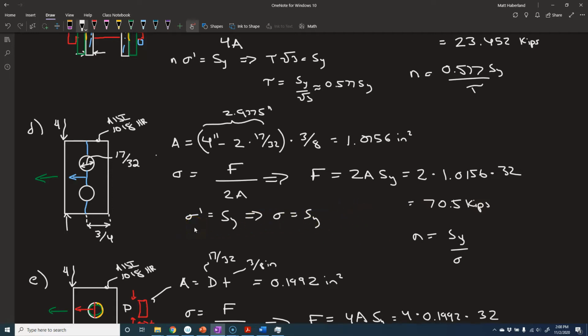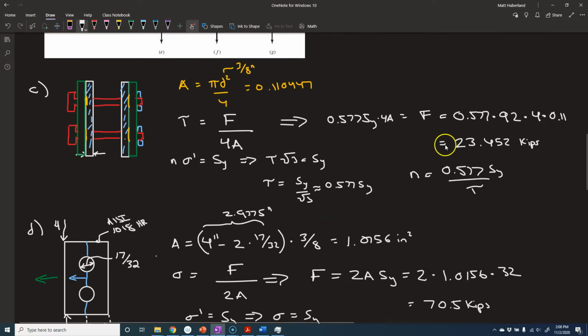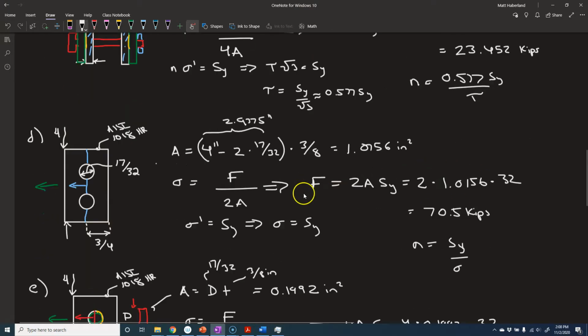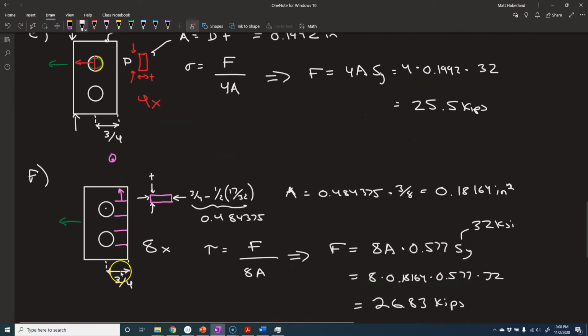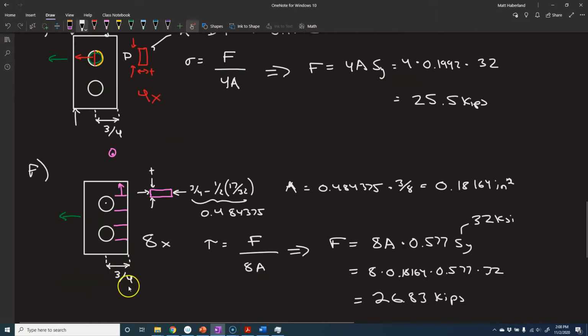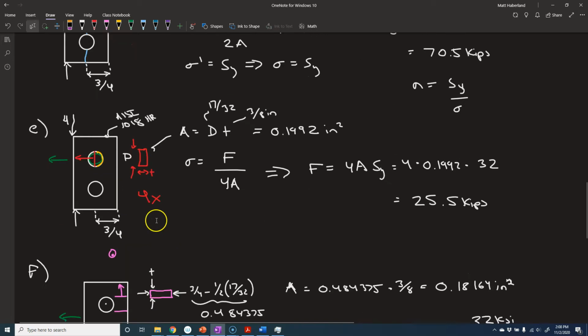You might be asked to size the bolts, and so you'd estimate a size, probably based on just taking a look at the shear strength of the bolts themselves. And then you'd size all the rest of it kind of by eye. Often they encourage that this is at least 1.5 times the diameter of the bolt if you've got the room. That's a rule of thumb that's not going to bother you. Once you've chosen the bolt diameter, you're just going to have to make sure that this material is strong enough to make sure it doesn't yield in bearing stress.